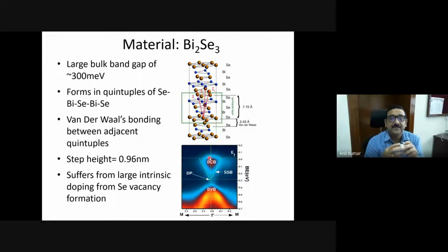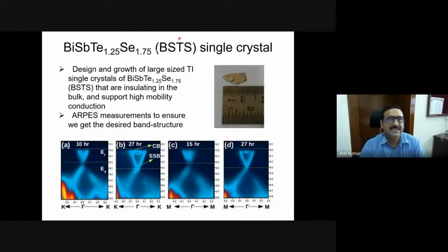This is because of the selenium vacancies. When I make this Bi2Se3, if there are selenium vacancies in the system, there is a kind of self-doping. So it is heavily n-doped, and the Fermi level gets into this region. Because of that, this is not a bulk insulating material, and we need to make a bulk insulating material for any of our studies. If you take another compound called antimony telluride, there the self-doping is such that it is a p-type conductor. So we start asking the question: suppose you have a material with bismuth, antimony, tellurium, selenium, can we tune the Fermi level so that it is in the band gap?